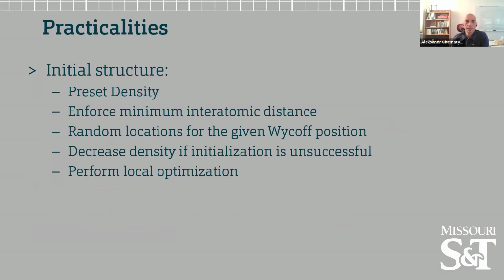Some practicalities, reasonably quickly. Initial structures play a very important role in this. We have an idea about what the densities of those compounds are going to be, so this is where we're going to start from. We're going to enforce the minimum interatomic distance because we know that atoms cannot be very close to each other. We don't have hydrogen or fluorine here, so we can survive on putting pretty strict restrictions on that. We're going to randomly place the atoms in the associated Wyckoff positions. For every given simulation run, we will pre-assign which atoms go to which Wyckoff positions in the primitive cell. If the search is unsuccessful for the random structure this way, then we're going to decrease the density, increase the volume, because that will relax the condition on enforcing minimum interatomic distance, and we will attempt to initialize again until we find the structure. And in the end, we will perform a local optimization from this point.